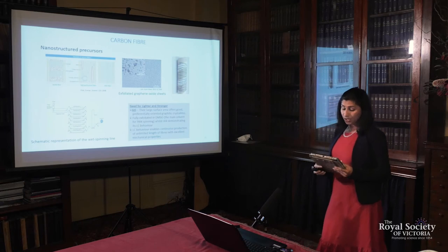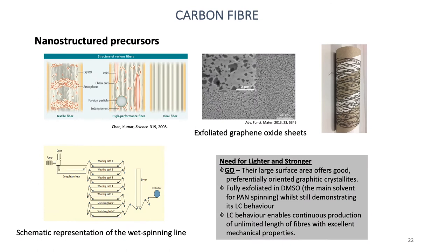My research was mainly focused in polymer synthesis as well as wet spinning to make precursor or white fibers. It has been reported that the quality of the final carbon fiber directly depends on the quality of the PAN fiber. Our target was to make high-performance carbon fibers. An ideal fiber will have very high strength, modulus, damage tolerance, and compressive properties. Though carbon fibers are high-strength materials, the mechanical strength of current carbon fibers is limited by the presence of voids, defects, and impurities. Theoretically, carbon fibers can be made 10 times stronger than currently available fibers.